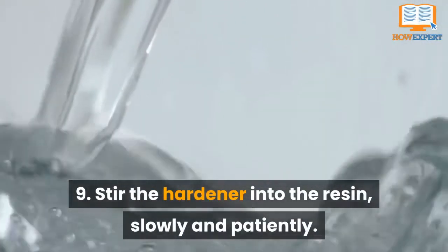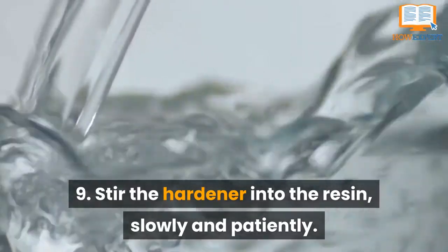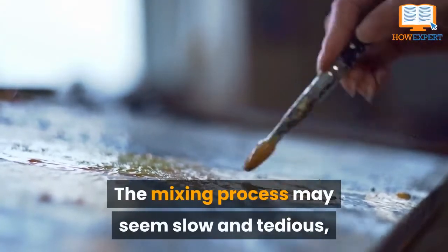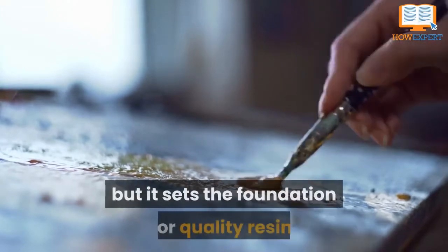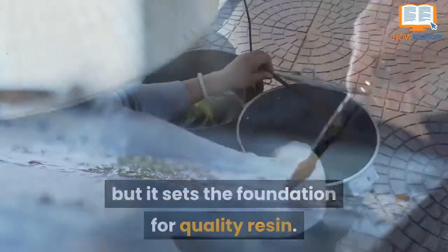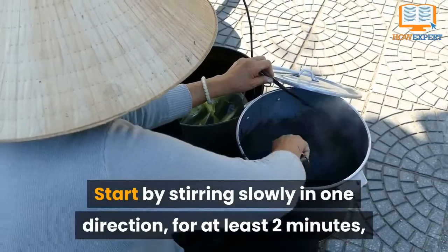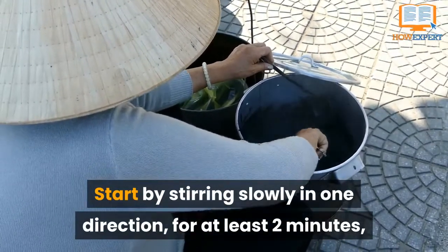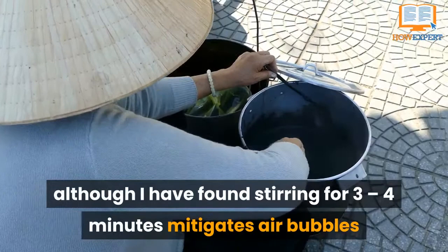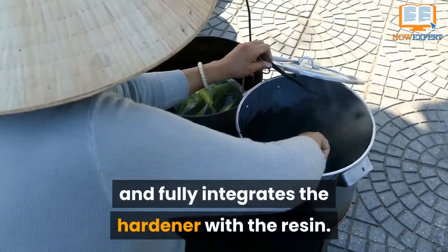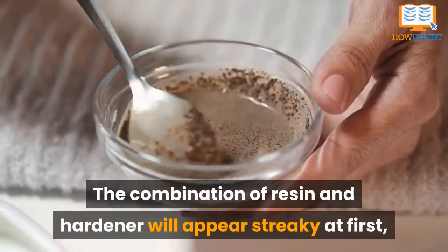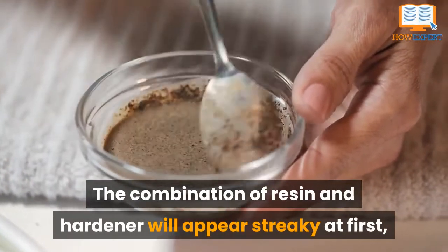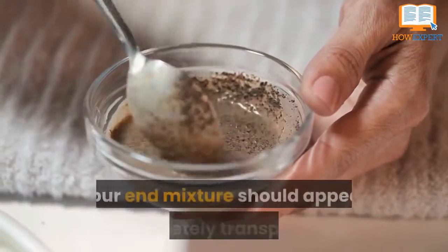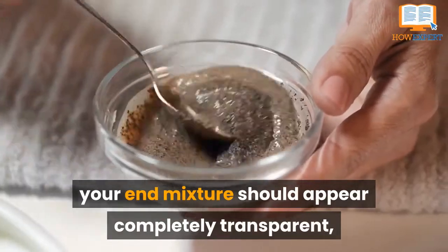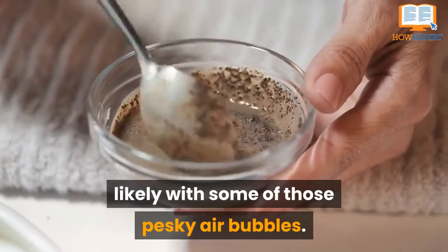Number 9. Stir the hardener into the resin slowly and patiently. The mixing process may seem slow and tedious, but it sets the foundation for quality resin. Start by stirring slowly in one direction for at least 2 minutes, although I found stirring for 3 to 4 minutes mitigates air bubbles and fully integrates the hardener within the resin. The combination of resin and hardener will appear streaky at first, but as the ingredients fuse, your mixture should appear completely transparent, likely with some of those pesky air bubbles.